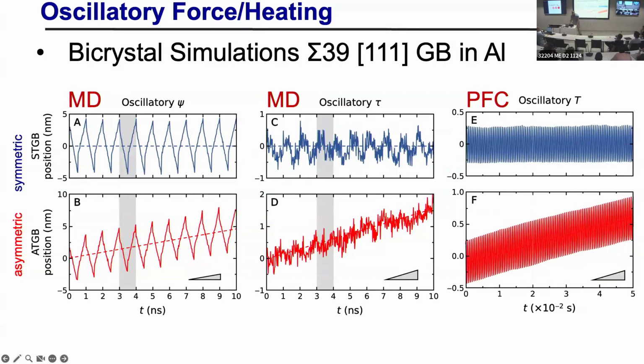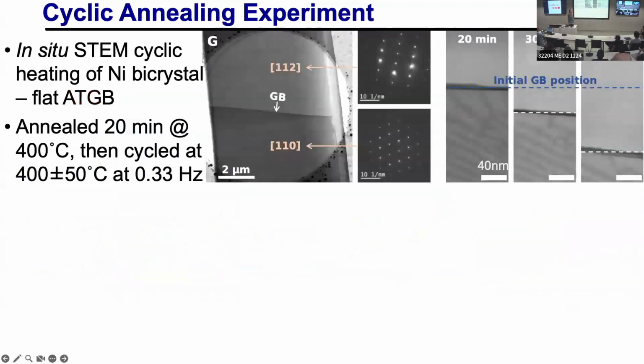Does it really happen experimentally? So my collaborators did a study here. What they do is they take a textured thin film of nickel. They do EBSD and measure the orientation of all the crystals. They find a grain boundary they like. They use a FIB to cut out a sample. So now they have a bicrystal.